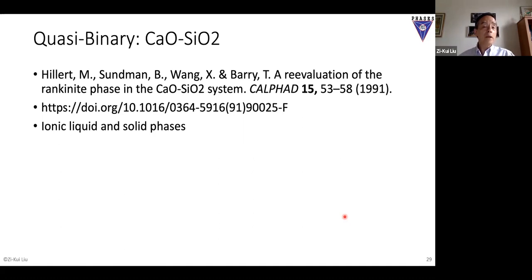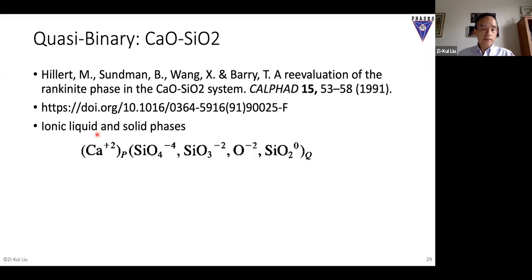But however, now we have an issue, which is that calcium and oxygen are charged species, right? So you have the ionic liquid and the ionic solid phase. So this is for the liquid model. You have calcium ions, you have silicon, but silicon does not exist by itself, right? Silicon is an oxygen species. And you also have neutral species too.